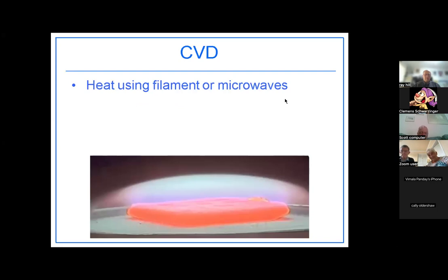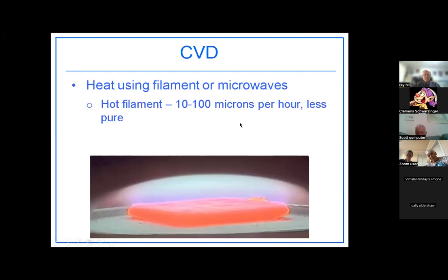Ah, excellent. Okay. So here you see the seed crystal, and the plasma of carbon atoms is hovering right above it. All right, so if you're using the hot filament, your carbon gets dissociated from your methane, and you can deposit up to 100 microns per hour, but it's less pure. Using the microwave, up to 10 microns per hour, but that results in a flawless crystal.